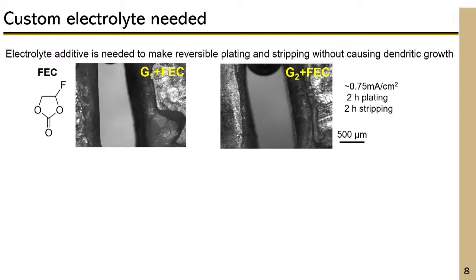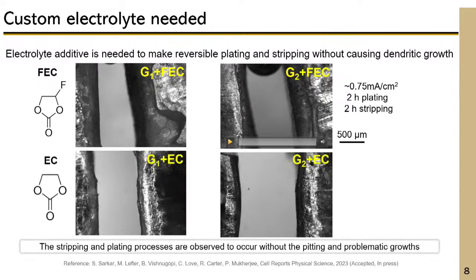So next, we thought that if we could replace this fluoroethylene carbonate with something cheaper and commercially available, already used in lithium systems, which is ethylene carbonate. Basically we removed the fluorine part and used ethylene carbonate as a solvent. We were running these videos, and we see that even with the addition of ethylene carbonate, there were no dendrites.